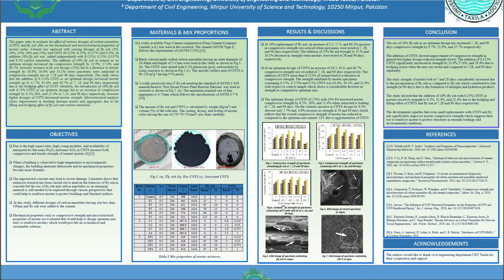When the optimum dosage of fly ash was combined with different dosages of carbon nanotubes, the best-performing sample contained 0.25 percent carbon nanotubes and 10 percent fly ash, which enhanced compressive strength at both 28 and 90 days. Microstructural analysis showed that these specimens had better bridging, with the matrix bridged by carbon nanotubes and a high amount of hydration products.